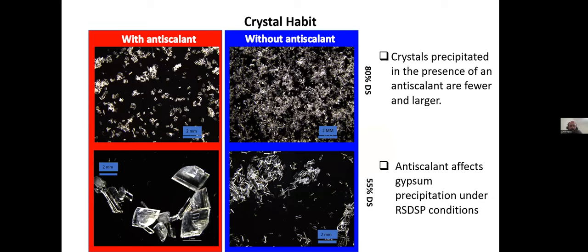And what we see is that the presence of scale inhibitors creates fewer crystals and larger crystals. So from the point of view of whitening, this is excellent, because if I have fewer crystals, they could contribute less to turbidity, and if they're larger, they sink faster out of the water column. It even lowers the possibility of a whitening event.